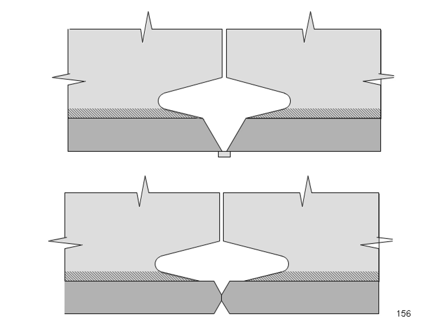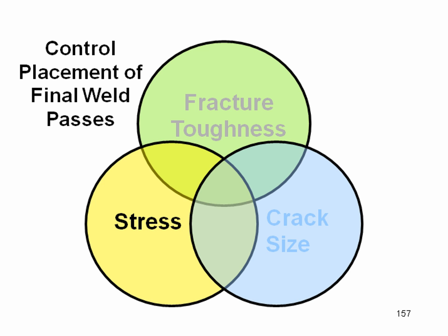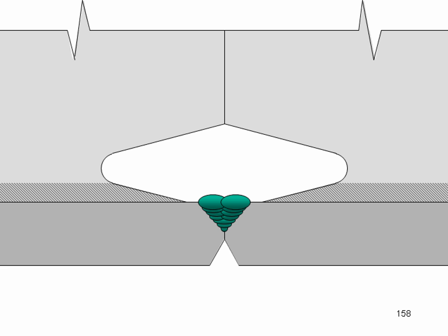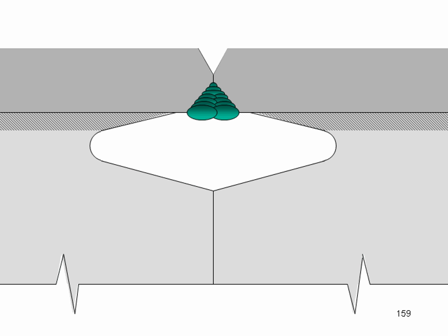Another issue is to remember that the last weld pass is the one that has the most significant tensile residual stresses. So by controlling the placement of the weld pass, I can improve the situation. Now notice this weld has been made on the inside of the shape first. When it's flipped over and I start welding on the opposite side, the members with the highest residual tensile stress are going to be placed out away from the area where the weld access hole is. So now I put the very problematic high tensile stress welds out away from the problematic area where we're cutting through the core and making the weld access holes.